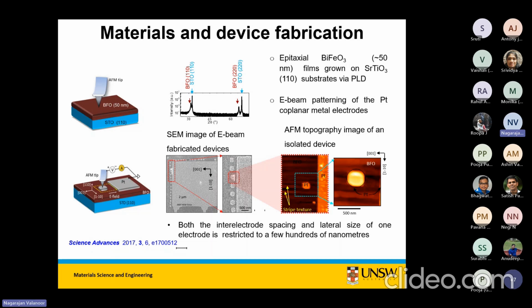Is that instead of growing 001, Pankaj, who was the lead postdoc, came up with this brilliant idea saying, actually, we should grow on 110 because then we can control the wall orientation much better. And he was bang on. Simply growing the BFO on 110 gave us that edge. Okay, nothing sophisticated, no fancy calculations, etc.